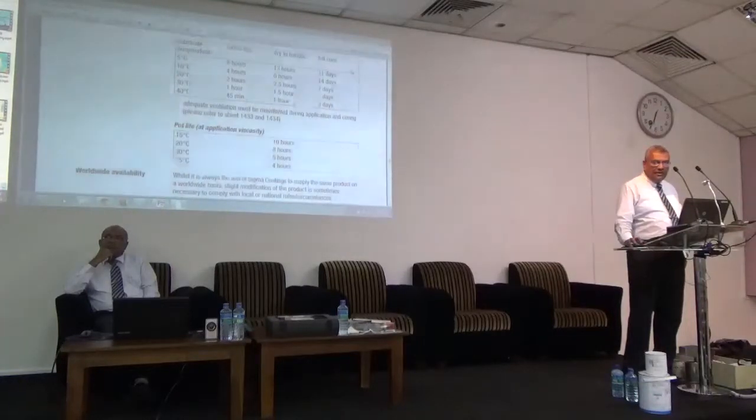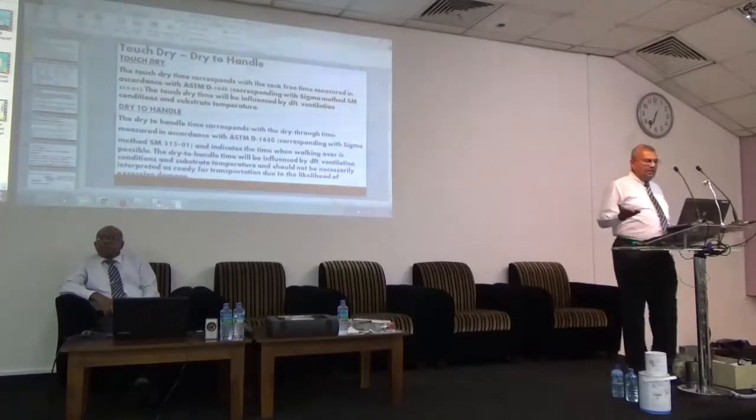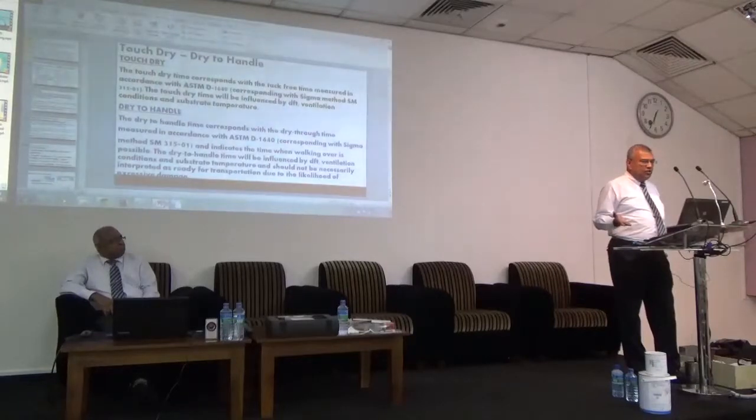Actually what we are doing is, without your knowledge of the data sheet, we are trying to define the meanings of these words. So now we have touch dry. Touch dry time corresponds to tack-free time measured in accordance with ASTM D1640. So you touch it and it's not coming off on the hand. That's a very simple thing.